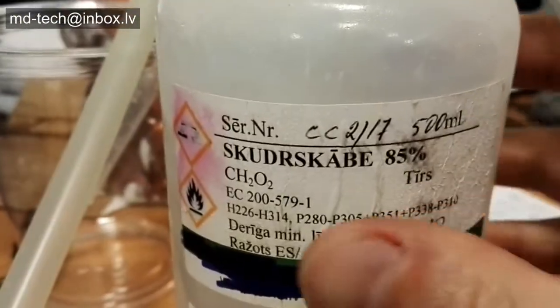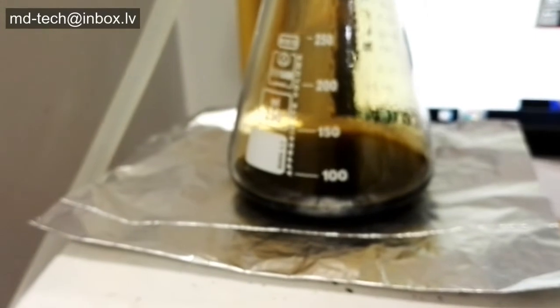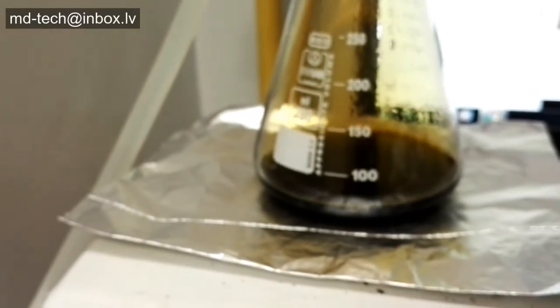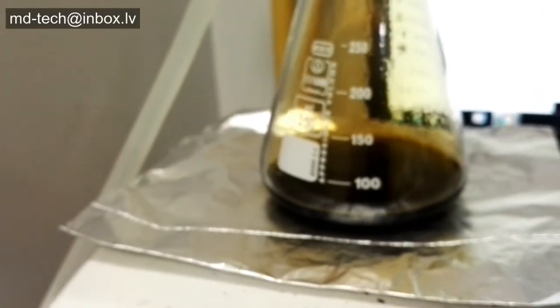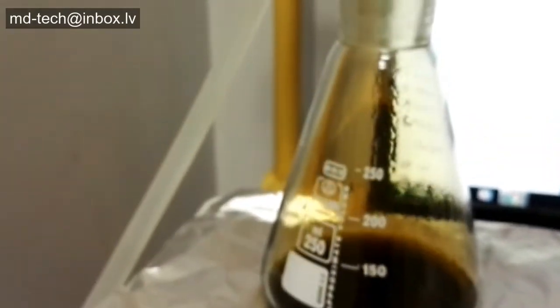Now it's very important to drive out nitric acid. I use formic acid and high temperature, 100 degrees Celsius, to start the reaction. Add a small amount at a time. If there are no brown fumes and lots of bubbles forming, the process is done.